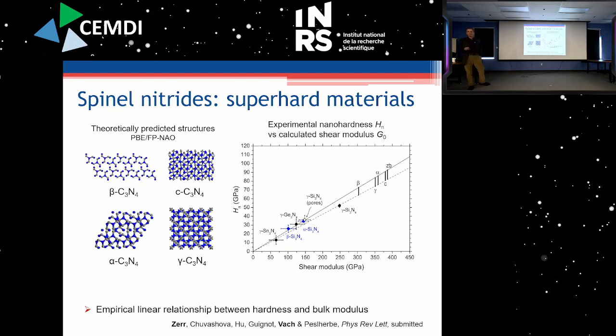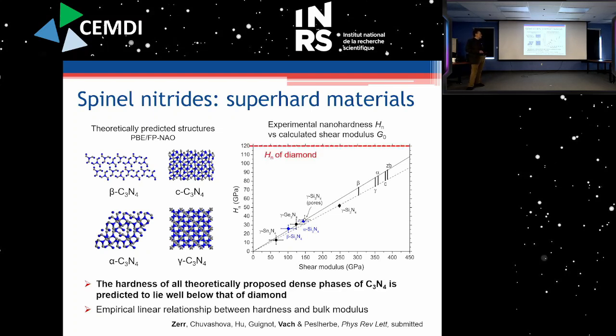And this was sort of a negative result in a way, because the goal in all this work was to try to find dense phases of carbon nitride that would be even harder than diamond, because that was the initial goal. And for a long time, physicists and engineers tried to look at different dense phases of carbon nitride and other materials, hoping to find harder materials than diamond. But unfortunately, fortunately for experimentalists, we can tell them, well, look no further. For these phases, it probably won't be as hard as you would like them to be.